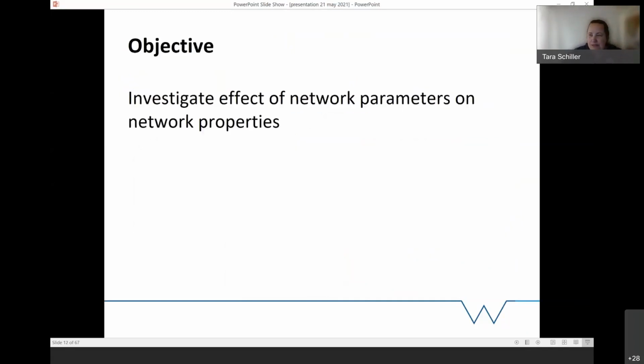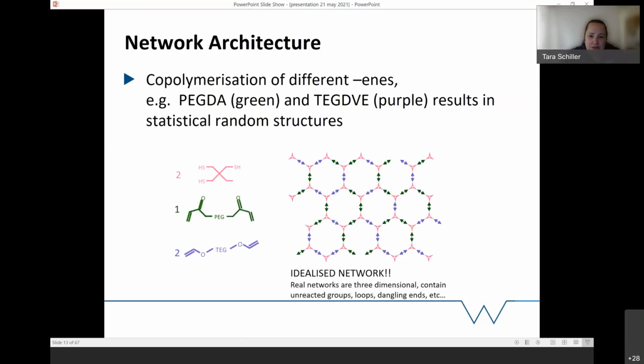So we're just trying to move away from off-the-shelf monomers and looking at ways that we can improve our systems. Yeah, we've got a lovely network here. If everything worked and went perfectly, this is kind of what it would look like. This is done by adding a photoinitiator, a catalyst, and curing at UV wavelength, at 365 nanometers. So we basically throw the three things in and out pops the network. So we get an elastomeric feeling polymer out of the end of it.